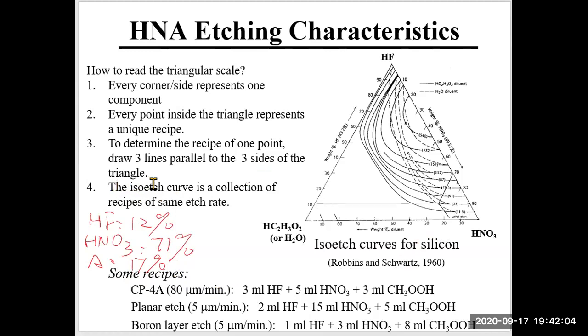Then the isoetch curve is a collection of recipes of the same etch rate. Those curves inside this triangle are called isoetch curves. We know that an isoetch curve is a collection of recipes of the same etch rate. That's the reason we call them isoetch curves. For example, this curve, which is labeled with 33. All the recipes along this curve have the same etch rate, which is 33 micrometer per minute. So this is the isoetch curve for this specific etch rate.